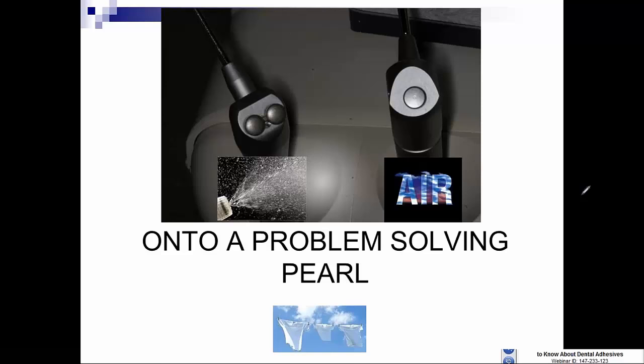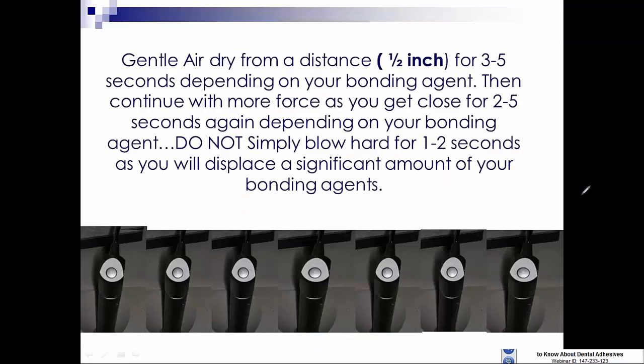that multiple flex syringe. So again, we want to gently air dry these self-etching materials from a distance, a half an inch or so, for 3 to 5 seconds, and that depends on your bonding agent. If it's an acetone containing bonding agent, that could be 1 to 3 seconds. If it's an ethanol containing self-etching system, probably 3 to 5 seconds is more important because ethanol is a little